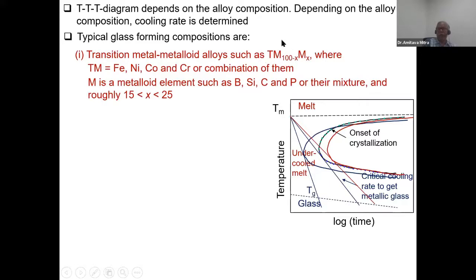What is this composition? One composition is the transition metal and metalloid, TM(100-x)Mx, where M is the metalloid. The transition metals we are talking about are iron, nickel, cobalt, chromium, or a combination of them, and the metalloid we consider is boron, silicon, carbon, phosphorus, or a mixture. Roughly this metalloid composition changes from 15 to 25, so that I can get a TTT curve such that cooling rate is within our limit.